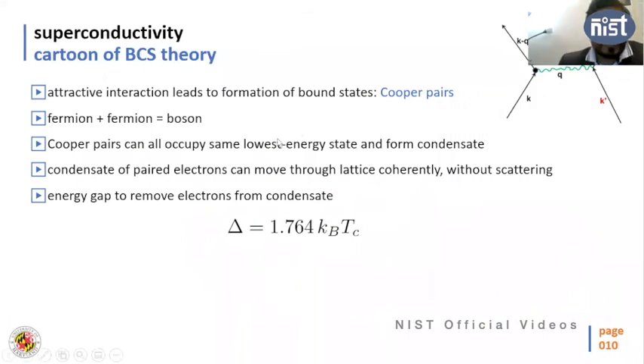So what happens in theory? It forms a Cooper pair, and two electrons, which are fermions, when you add them together and they form this pair, Cooper pairs, it becomes a boson. That allows all these Cooper pairs to occupy the lowest energy state, the same energy state, and pass through the solid without a loss of any energy. Basically, resistance becomes zero. And in theory, it was found that it forms a gap. It opens a gap in the Fermi surface, which is delta, defined by these equations, and the Tc is directly connected to this energy gap.